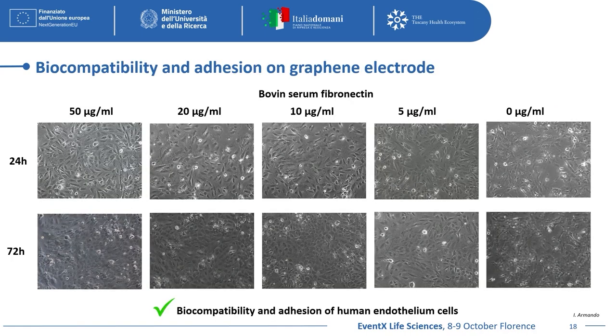So now we are trying to realize the BBB again with different kinds of electrodes inside the device, and we performed some preliminary tests to evaluate the biocompatibility and the adhesion of the endothelial cells, mainly on the graphene electrodes. We obtained quite good results, but because of the hydrophobicity of graphene, the cells are not able to attach without any coating. So we tried fibronectin, and we observed that even with a very low concentration of fibronectin, we are able to obtain a quite homogeneous layer of endothelial cells.